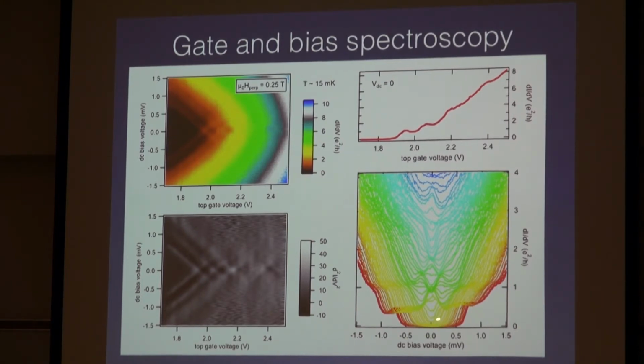At zero bias, you see a collection of the current peaks around 0, 1, a little bit at 2. It's a little less than 2 here. But what's interesting is that when you go away from zero bias, you see these half plateaus. So there's a collection around half e²/h, more so, a little less so, around 1 e²/h. And this comes when you actually have quantum confined levels and you move. So what the voltage spectroscopy does is move up, down the Fermi energy of the leads. When you move into a region where you have 2 confined levels in your quantum point contact, you get this half e²/h plateau. And so I think this is very convincing that this is, in fact, quantum point contact-like behavior.